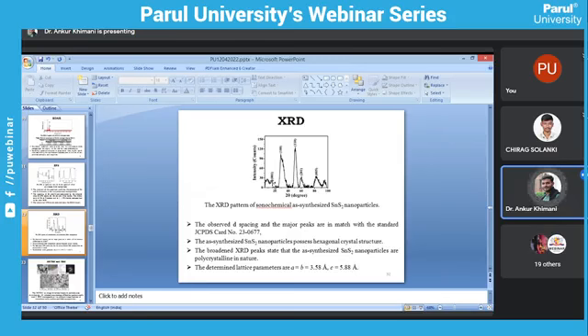The synthesized SnS2 nanoparticle possesses a hexagonal crystal structure. The broad XRD peaks state that the synthesized SnS2 is polycrystalline in nature. The determined lattice parameters are a equals b equals 3.58 angstrom, c equals 5.88 angstrom.